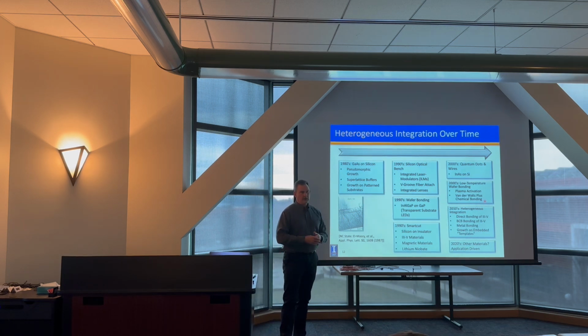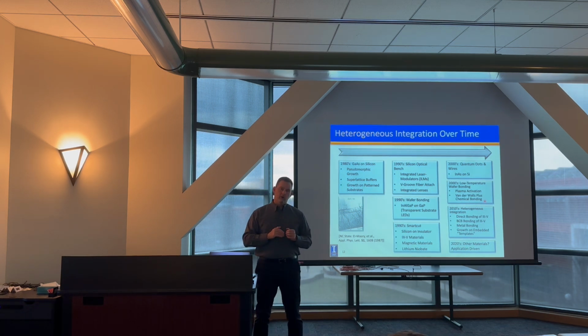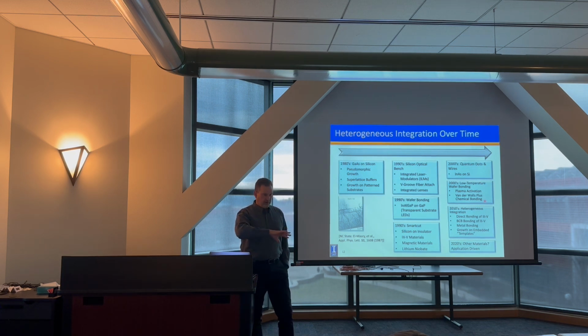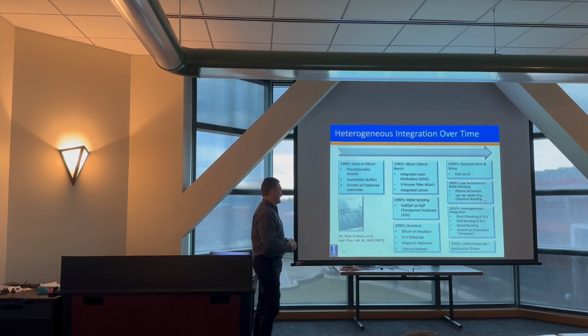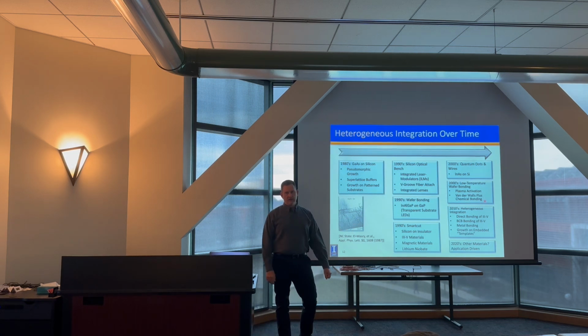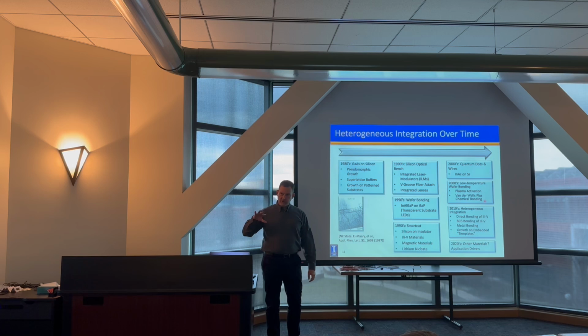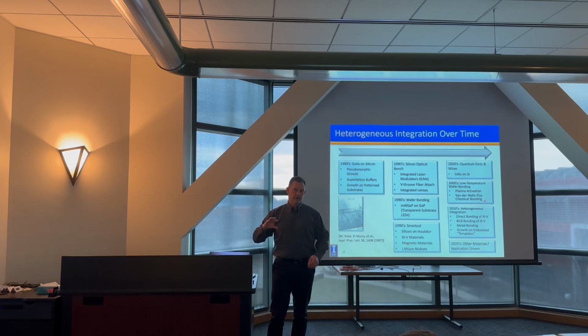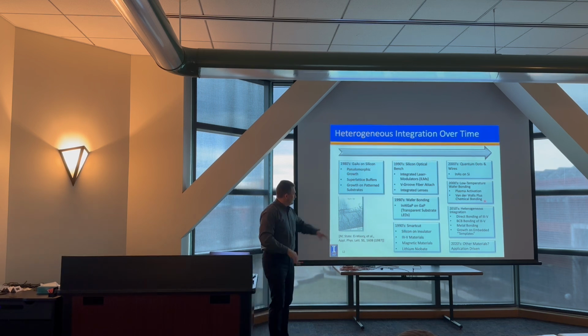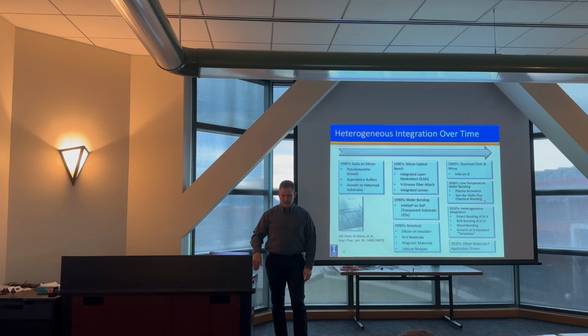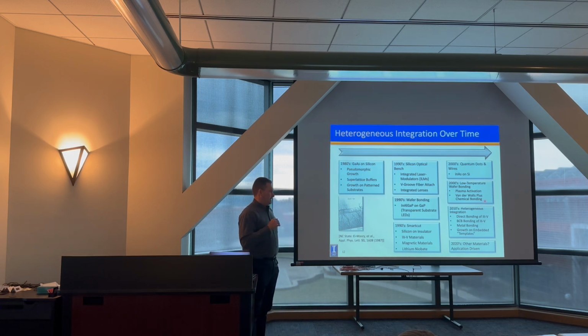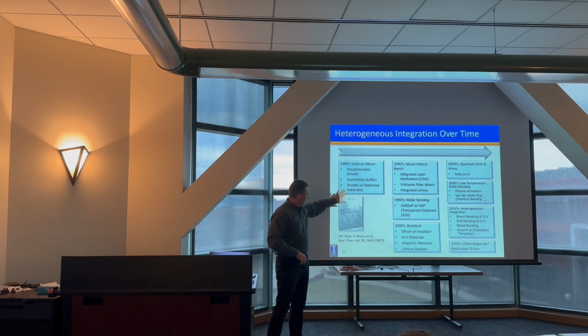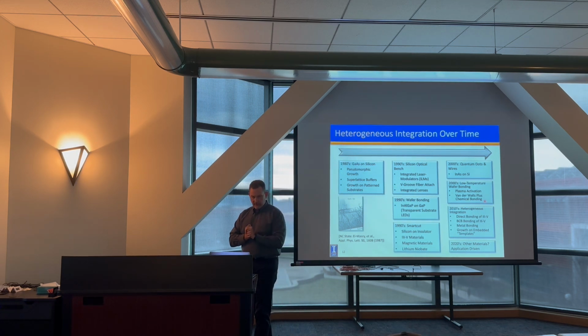Even if I do tricks, like having superlattices or, in the growth process, varying temperature to try to bend your dislocations over, I still have this huge dislocation network sitting below my device. And eventually, when that dislocation grows due to heat and light driving the defect into my active region, it's going to explode and my device is going to die relatively rapidly, okay? Regardless of what I try. Pseudomorphic growth, superlattice buffers, growth on patterned substrates, light and heat drive dislocations. So this was a focus for a long time, but ultimately, it had problems.